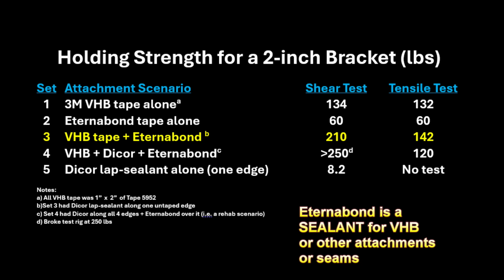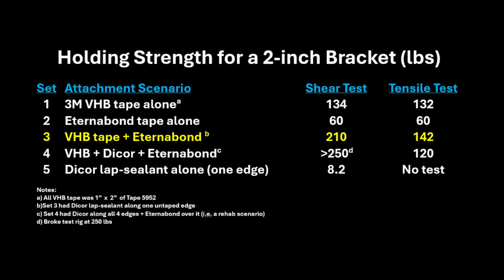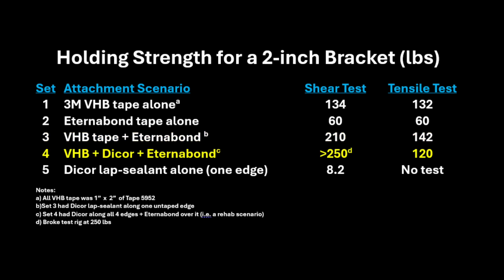Set number 3 suggests that Eternabond adds to the VHB strength under a shear load, but does not add much under a tensile load. Set number 4 shows that putting Eternabond over an old VHB and lap-sealed bracket to rehab it can be very strong against a shear load, but not add much against a tensile force.